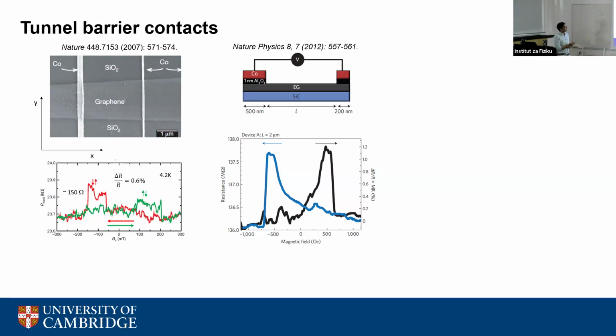Now, this is in principle a nice device, but the main challenge is it is really hard to make these devices, because if you want to deposit a tunnel barrier, it should be less than a nanometer thick. But growing 1 nanometer Al2O3 on graphene is a real challenge, because graphene is very flat, you have no defects or no dangling bonds, and you really cannot make these atoms nucleate. So when you create these films, they are full of pinholes and defects. So you cannot grow very nice continuous atomic dielectrics on 2D surfaces. So if you want to grow them continuously, you have to make them thicker. So here they have used 1 nanometer.